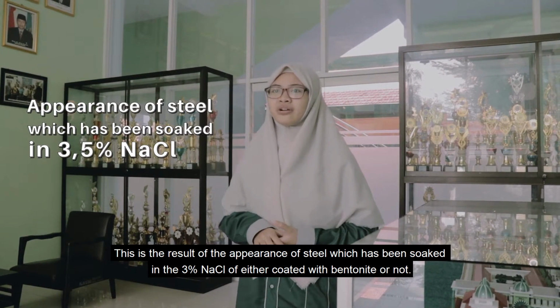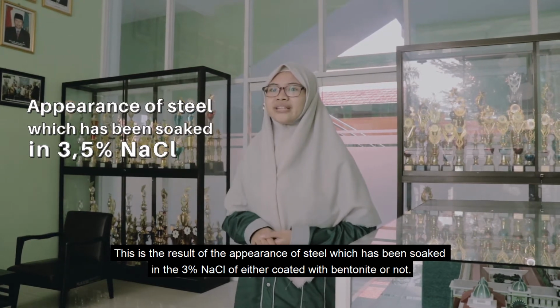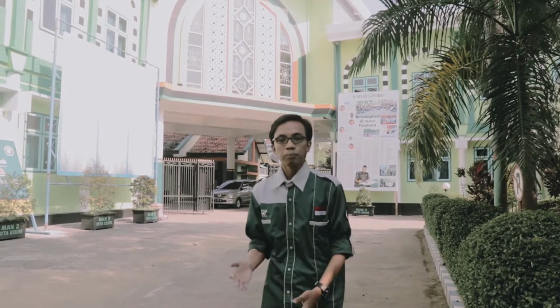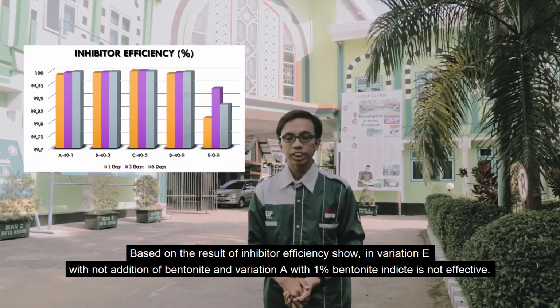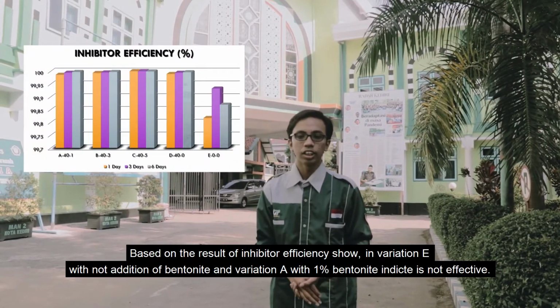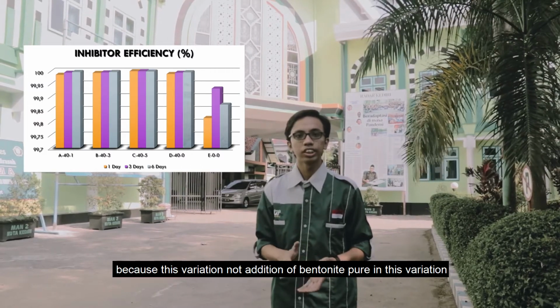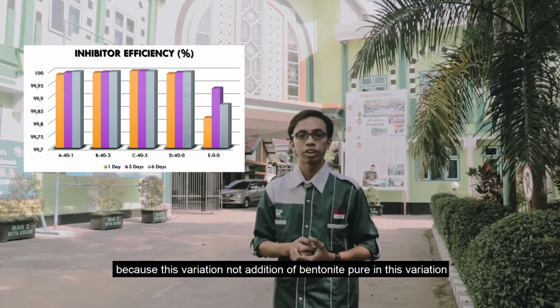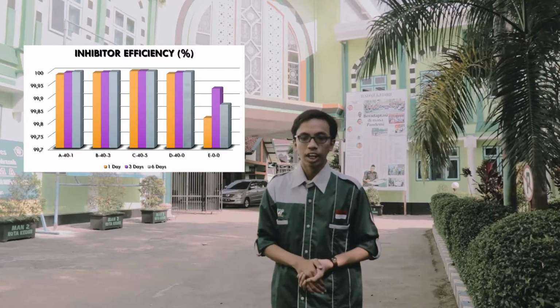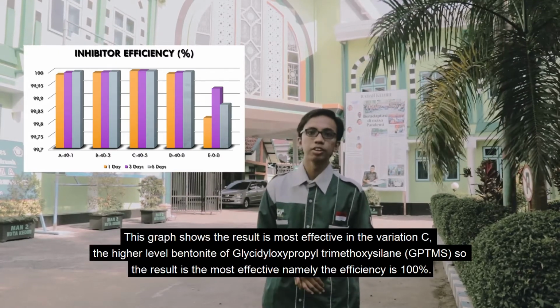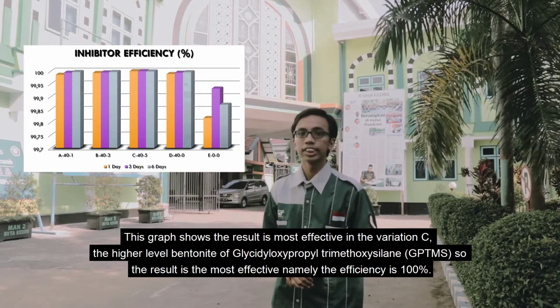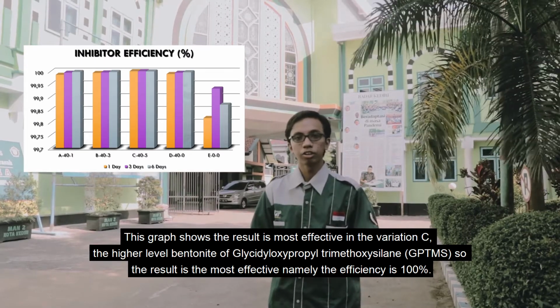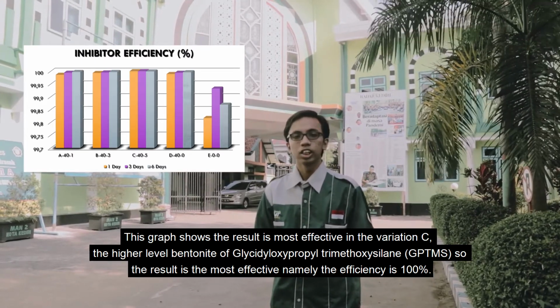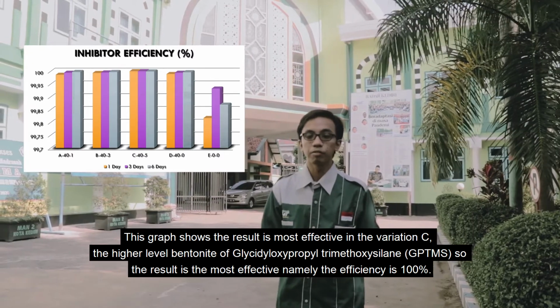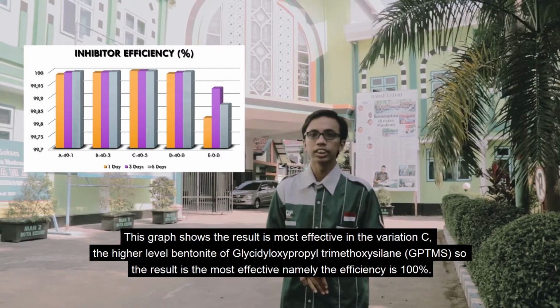3.5% sodium chloride, either coated with bentonite or not. Based on the result of inhibitor efficiency, variation A is not effective because this variation has no addition of bentonite. This graph shows the most effective result is in variation C, with the higher level of bentonite with GPTMS, so the result is most effective, namely an efficiency of 100%.